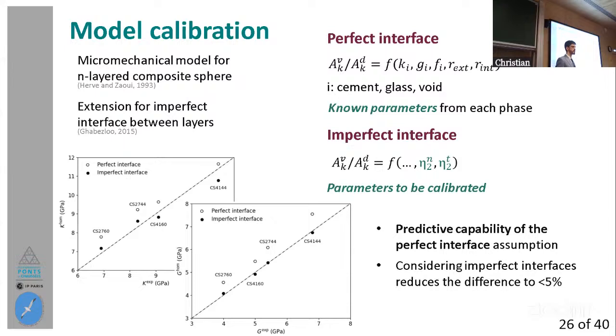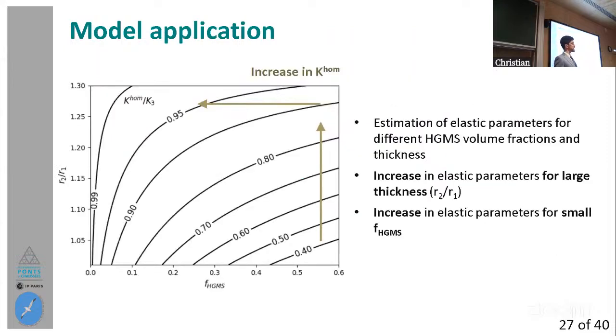And there you can see already that we have quite a good predictive capability of the model without calibrating anything, leaving it only analytical. But we were able to improve it a bit, considering the imperfect interface and this possible displacement between phases, which is noted here with the black points, in which we can see that they are much closer, both in K and in G, to the diagonal line, which means an almost complete agreement between model and experimental parts.